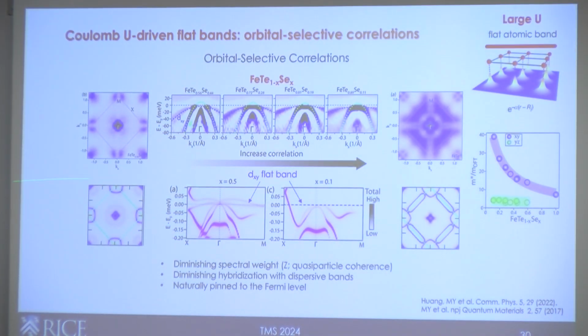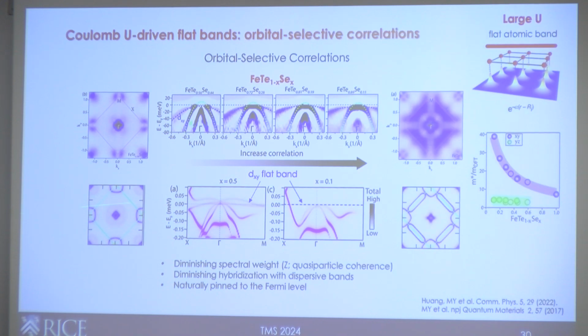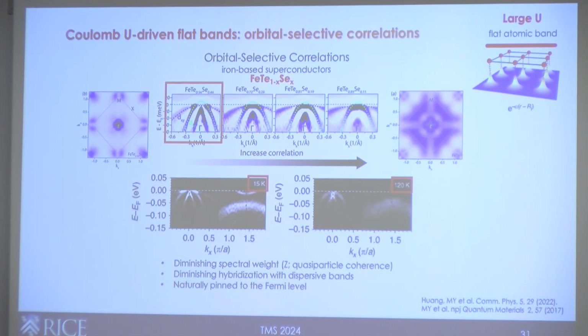And this calculation comes out of the slave-spin calculation. You see that without any symmetry-breaking phases, you actually see the Fermi surface shape change. And that's exactly what we see experimentally from photoemission. We see the small pockets on this side, and then these large things on that side, which indicates that this band becomes extremely flat, but it loses all spectral weight. So this is one type of flat band, by cranking up U. And then I think Lenny also mentioned that as a function of temperature, you should also see some disappearing of these quasi-particles, and indeed we see that.